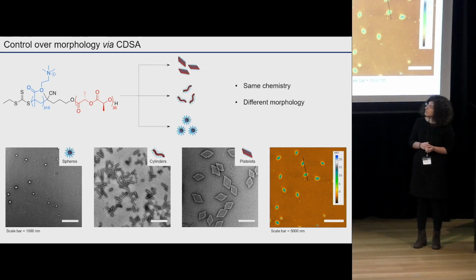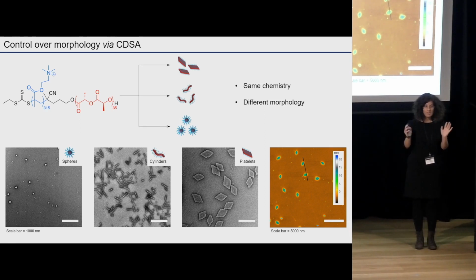And so the polymer that I designed was this one here. This has a polylactide core as opposed to polycaprolactone, as I showed before. Polylactide is, again, a biocompatible and biodegradable polymer, and it's a slightly different chemistry for the hydrophilic block. But the key point here is that we can use the same polymer, the same chemistry, to make 3 different morphologies: spheres, cylinders, and platelets. So any property that we see from the particles from now on is only because of the nanoparticle morphology and not because of its chemistry.